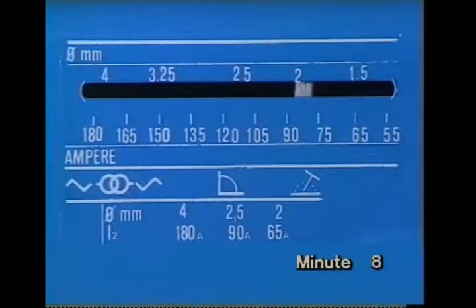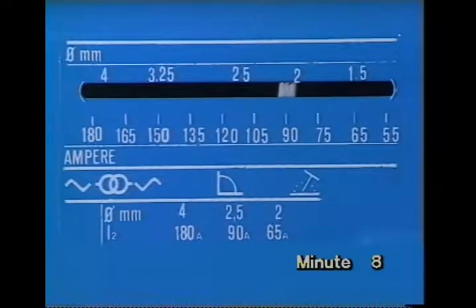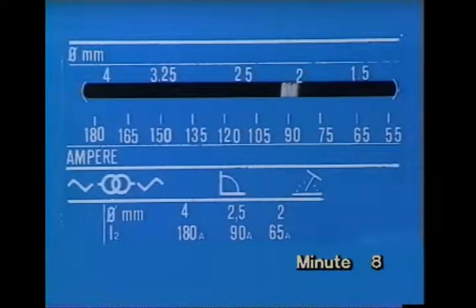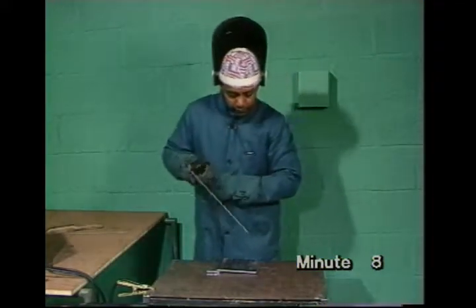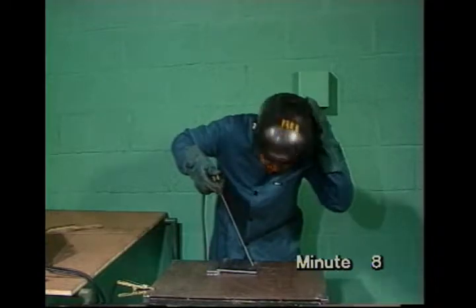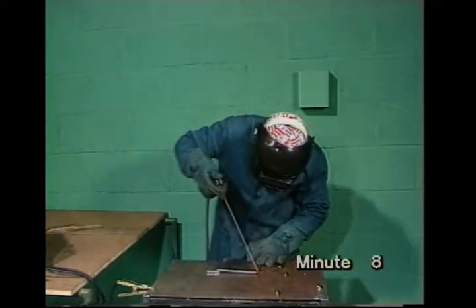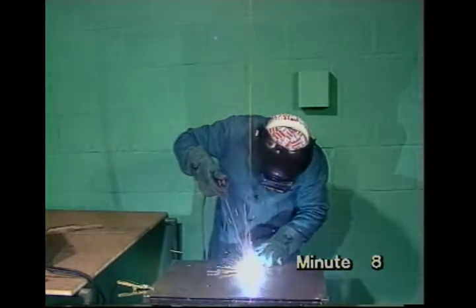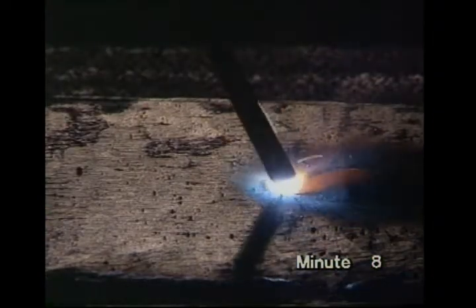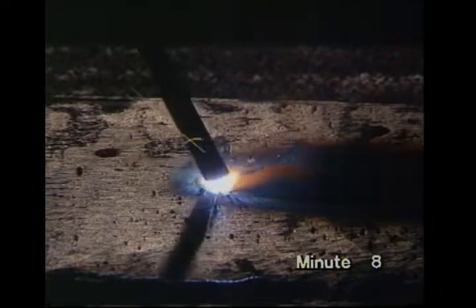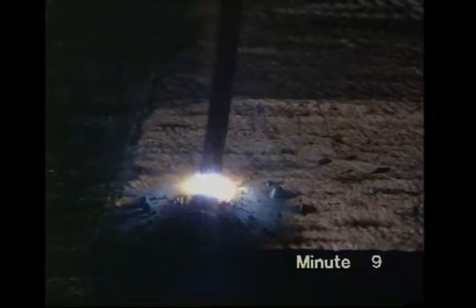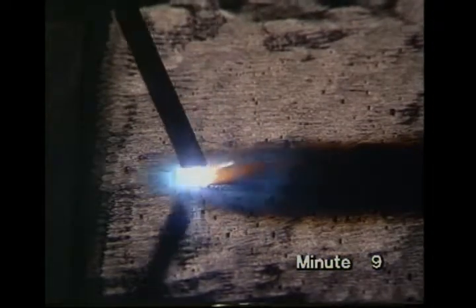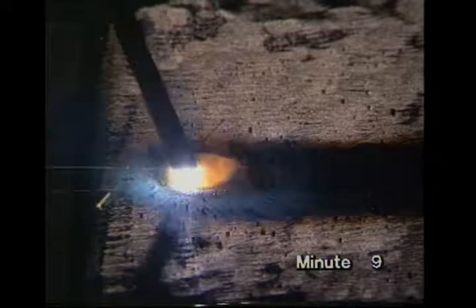Set the current to about 90 amps and switch on. Make sure you have your welding shield in position, then strike the arc. A correct run will look like this. Note the arc length. You should try to keep it about 3 millimeters long. This is what you should see from your position. To stop, backtrack over the end of the weld bead, then pull the electrode away sharply to break the arc, exaggerated here.